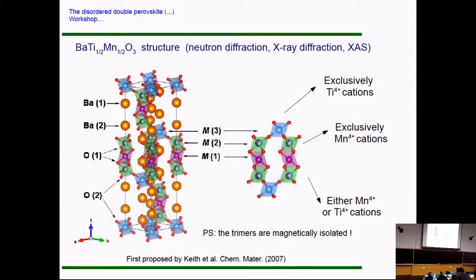And the idea here is that if you simply work out the stoichiometry, if this is exclusively occupied by manganese and this is exclusively occupied by titanium, the mixed occupancy here should be really half-half. So half the sites are occupied by titanium, half the sites are occupied by manganese. This is the way it should be, so you can keep the stoichiometry right. There is no other way to do it, right? And here, if you do the charge balance, you think that it's manganese 4+.